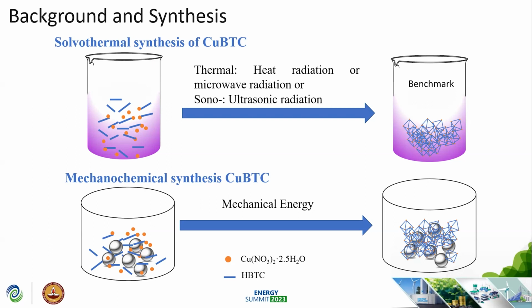However, in this method, they have some problems. For example, they require a longer reaction time and they need a lot of solvent to promote the synthesis. So as a result, it will cause energy waste and solvent waste. In order to solve these two problems, in my research, we explore the mechanical synthesis of copper BTC. In this method, the energy will be provided by the crush between the materials, the balls, and the milling jar. In this method, we only need maybe 1 minute or 3 minutes. We can get the copper BTC, and we don't need to use the solvent to promote the synthesis. So it will solve the problems that exist in the thermal synthesis.